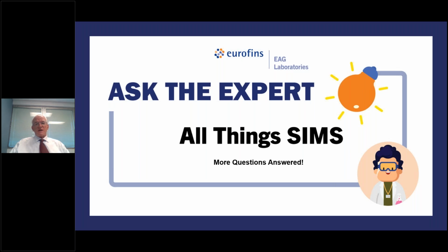But I want to draw a difference between EDS and WDS, which is wavelength dispersive spectrometry. WDS does use standards. Instead of using a silicon surface barrier detector to determine the energy of the X-rays, you use a crystal spectrometer. And the WDS can be very quantitative. We often use WDS to quantify some of our standards that we use in SIMS. So EDS, basically no standards, and SIMS, standards. But if you don't have standards for SIMS, then you can be telling huge lies, like orders of magnitude. So you have to watch it.